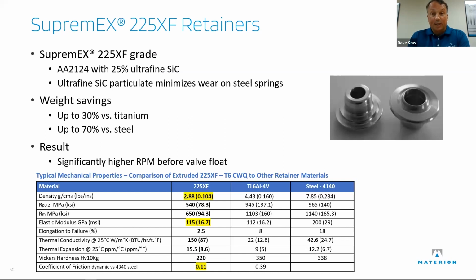And that means, as you know, if you can lighten any part of the valve assembly, you can get higher RPMs before you hit valve float. And so, as you can see, compared to titanium and steel, the density is fractional. I mean, it's a lot lower density than either of them. The elastic modulus, it's stiffer. This material is stiffer than titanium. Now, you still have to beef it up a little bit for strength reasons, for the fatigue, but also it has a very low coefficient of friction. So it reduces the drag on the top of the spring. And you'll see on the next page how they got a little bit thicker.